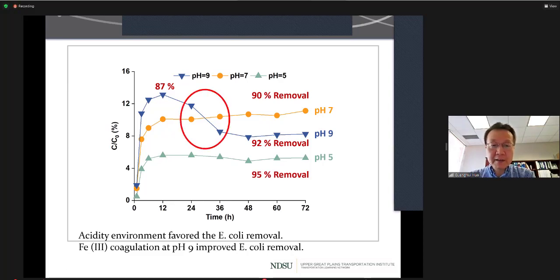And we attributed this phenomenon to the ferric coagulation impact. We observed that some of the dissolved iron were able to coagulate E. coli and form a deposit. That's what we observed from the column study. So basically, in addition to the filtration and adsorption impact, we found that at high pH values, the dissolved Fe is able to coagulate and form floc that could trap E. coli from the water.